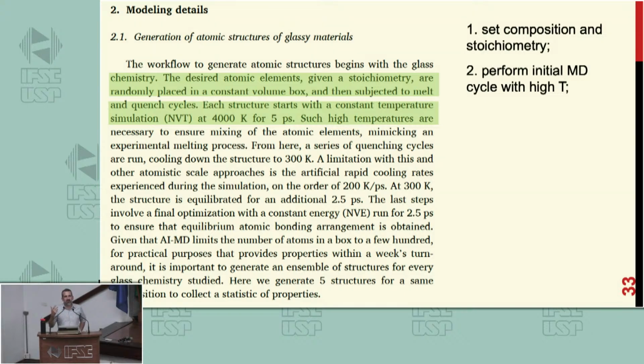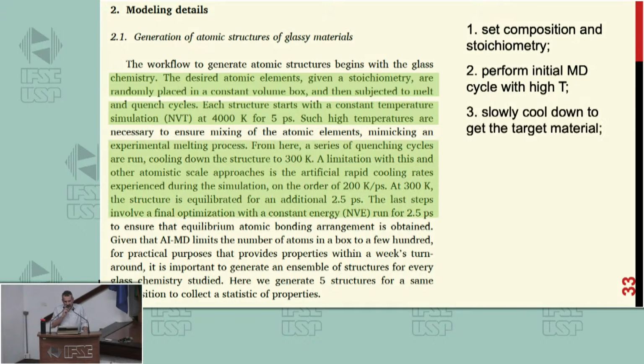So this is very tricky, and sometimes because of this kind of approximation, you will not get a very good number for these temperatures. So that's why they start with a very high temperature, 4,000 Kelvin. They leave it there for some time, okay? Afterwards, they start quenching. They start decreasing the temperature.